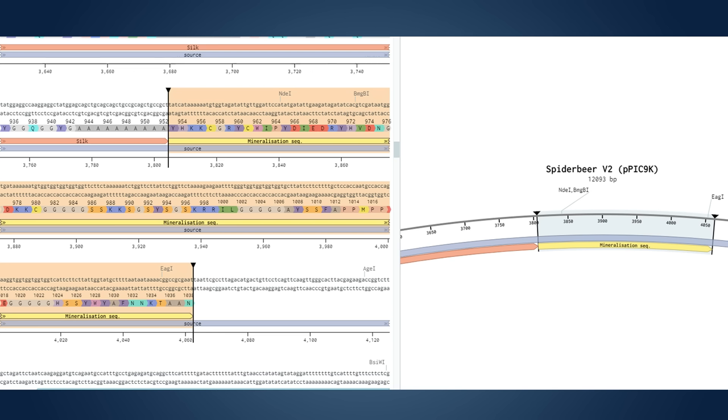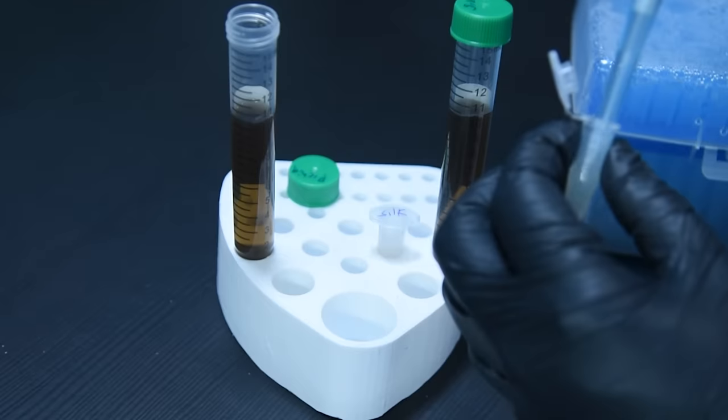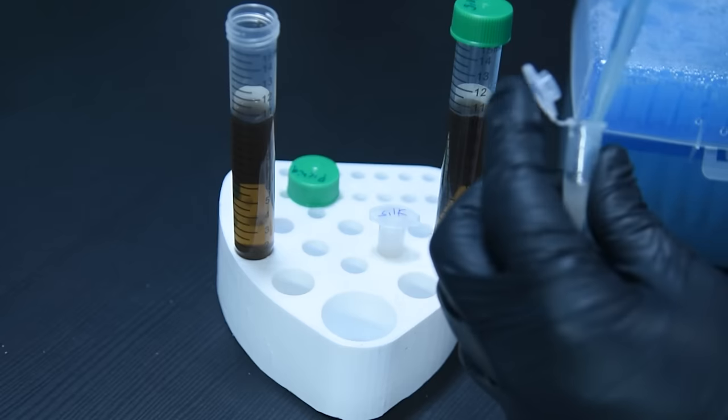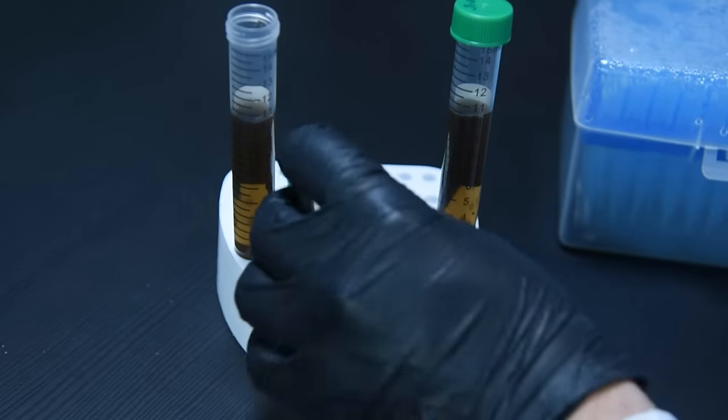Now, because of the graphene-binding peptide on the end of the silk gene, when I add the silk solution to it, it should all clump and crash out. Whereas with the plain yeast, it should leave the graphene in solution. I added 1 milliliter of each yeast sample to their respective graphene solutions, and then gave them a mix.